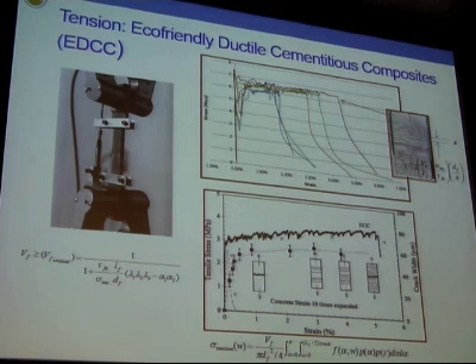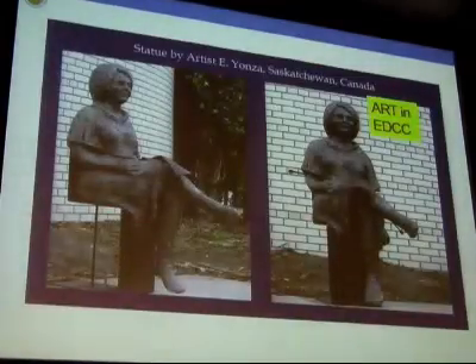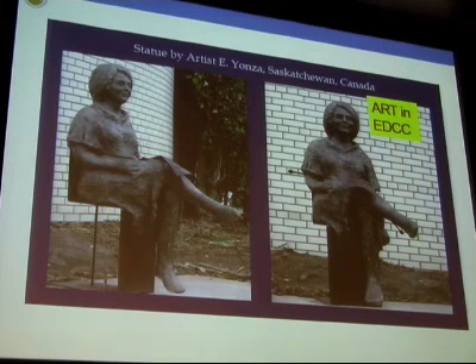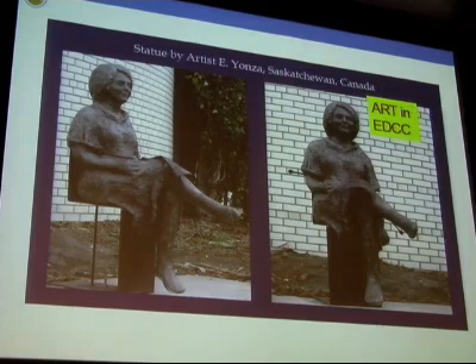And the great benefit of making them eco-friendly is that these are utilizing large amounts of industrial byproducts, such as fly ash, metakaolin, and blast furnace slag. So we are trying to reduce the cement content. Cement, as you know, is a very dirty industry. It produces up to 7% of global greenhouse gas emissions. So what we are trying to do in these composites is reduce cement as much as possible. Clearly, these are quite eco-friendly, and they are also highly ductile. And just to give you a look at what EDCC, or eco-friendly ductile cementitious composites, can do, these are statues that have been built in Saskatchewan, Canada, utilizing the EDCC I just described.